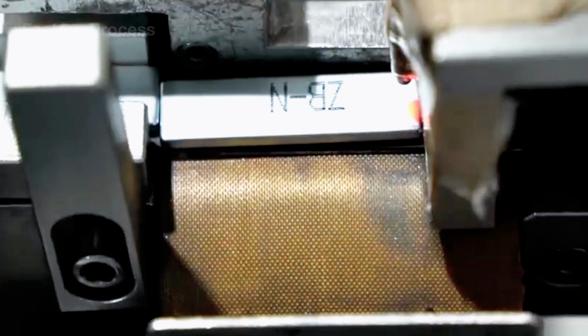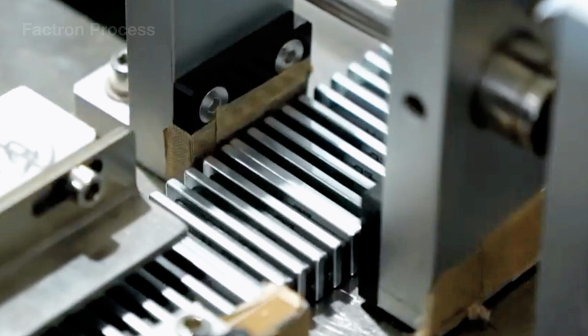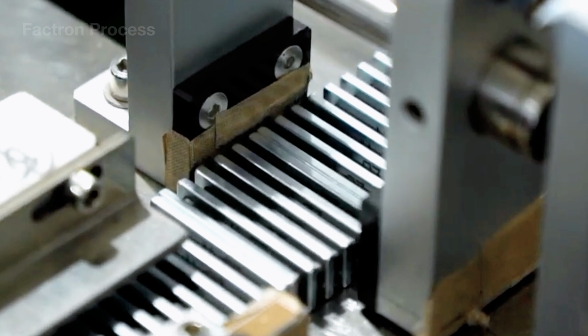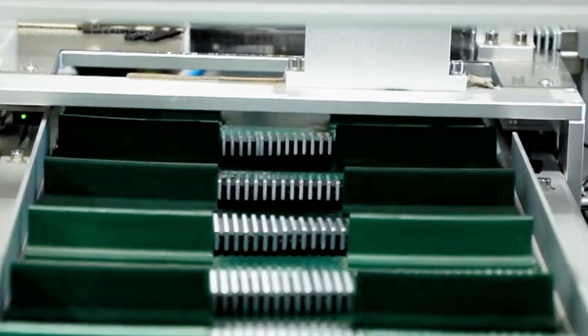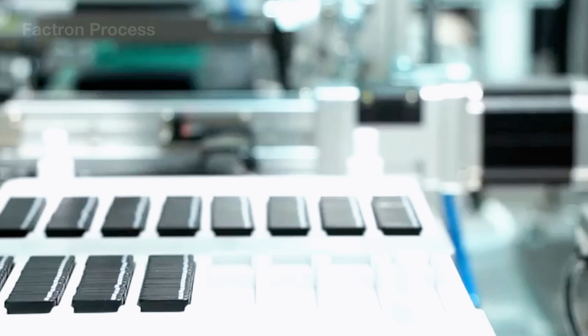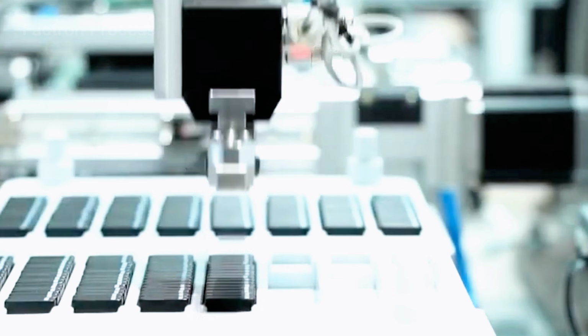Each magnet is then checked using Gauss sensors, Hall probes, and flux measuring equipment. Machine vision detects cracks, chipped edges, and coating defects. Representative samples are also subjected to heating and salt spray tests, while rejected products are demagnetized and transferred to the recovery line.